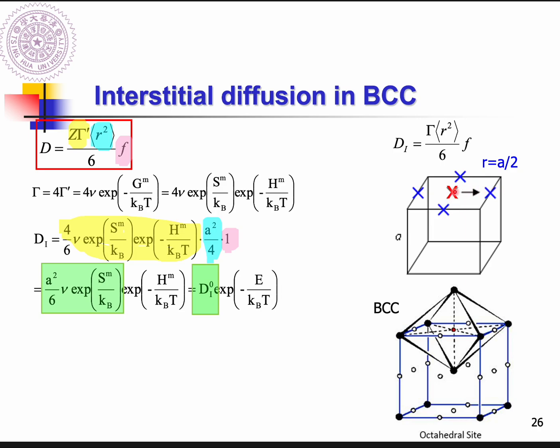between two interstitial sites, you just need to figure out the shortest jumping distance, which has a higher possibility for the interstitial to jump to. So we just consider the shortest location or site. For this interstitial site, there are only 4 nearest interstitial sites nearby. And this one for sure is longer than this one, right?